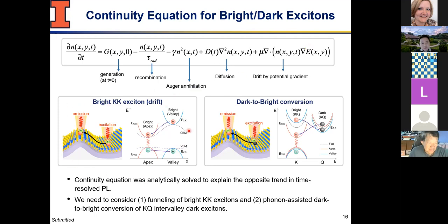So that's what this really shows, right? If you have an energy gradient, so let's say your valence band is equal, so you don't need to worry too much about that. Your conduction band basically gets a lower energy. So if you're an exciton, you want to drift towards a lower portion of the material. How far you go, right? Those are really interesting questions. That's what this model and our measurement can help understand.